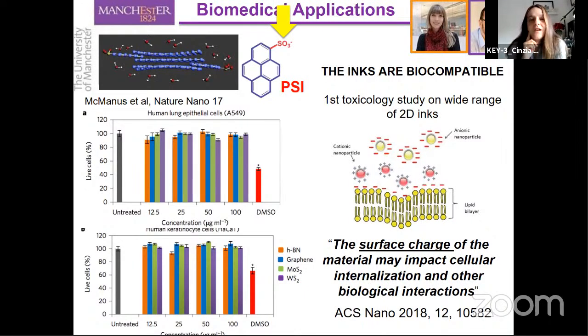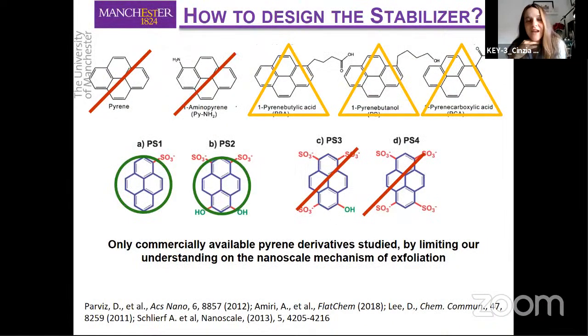And in principle, we could simply change the pyrene derivative to change the surface charge of our dispersions. And in practice, this is not so simple because exfoliation with pyrene derivatives is not fully understood yet. We know that certain pyrene derivatives work well, others do not work at all, and others are able to exfoliate, but usually produce low concentration or weakly stable dispersions.